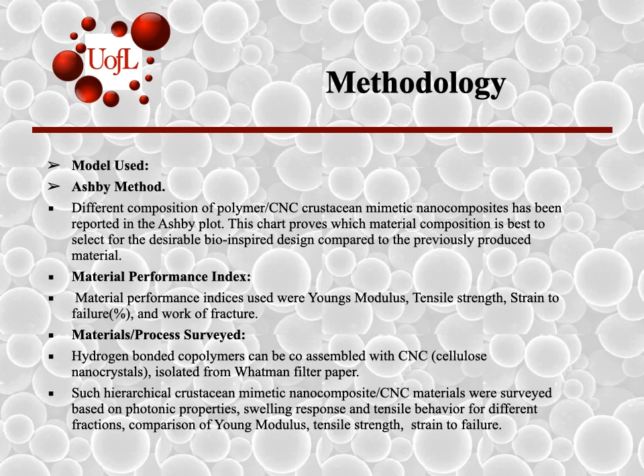For the methodology, the authors used the Ashby method. Different compositions of polymer CNC nacre-mimetic nanocomposites have been reported in the Ashby plot. This chart proves which material composition is best to select for the desirable bio-inspired design compared to the previously produced material. The material performance indices used are Young's modulus, tensile strength, strain to failure, and work of fracture.